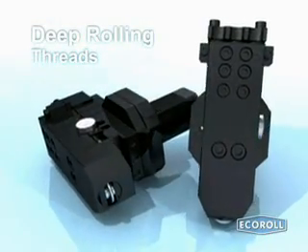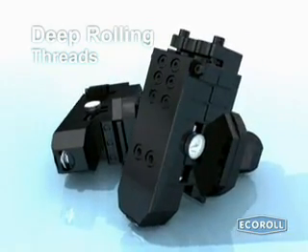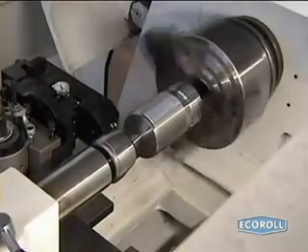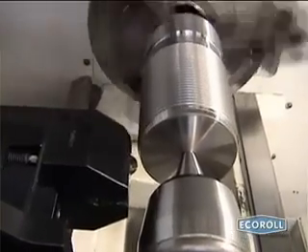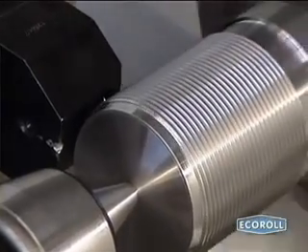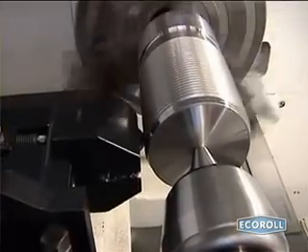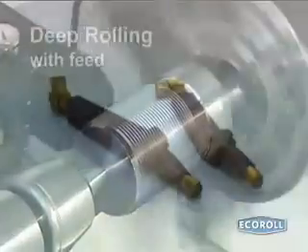Threads play an essential role in oil industry applications. They function as connecting elements in boring rods, in mechanical or hydraulic presses, and in die-casting or injection molding machines. Because these threads are subject to high dynamic loads, material fatigue can cause them to fail. To improve thread durability, Ecoroll's EF-90 deep-rolling tool introduces residual compressive stresses to increase local fatigue strength. The process often achieves a significantly increased endurance limit while simultaneously smoothing the thread's surface. The EF-90 tool machines workpieces on the lathe directly after the cutting process.